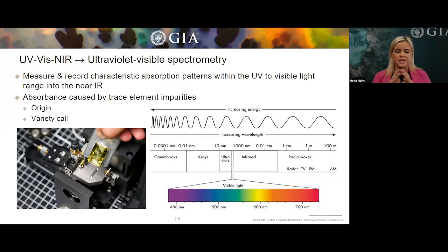Okay, so the next advanced testing machine we have is our ultraviolet visible spectrometer, or UV-Vis. Here the machine will measure and record absorption patterns within the UV to visible light range and into the near IR. When we look at the absorption patterns in the UV-Vis spectrum, what we are analyzing and looking for is absorptions caused by trace element impurities. And so the collected spectra contribute to our origin calls for blue sapphire, to help us guide if it's metamorphic or magmatic origin.